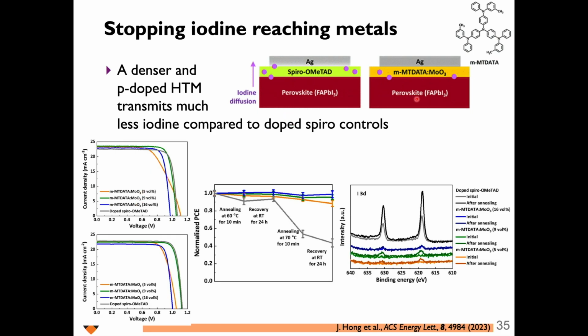In this case, we took a pretty well-known hole transport layer from the OLED field, and it's readily doped by moly oxide. It's also readily doped by iodine. But if we co-evaporate this compound, m-MTDATA, with moly oxide, we strongly p-dope it, and we also increase its density. And the action of pre-doping it with moly oxide really holds back a lot of iodine.